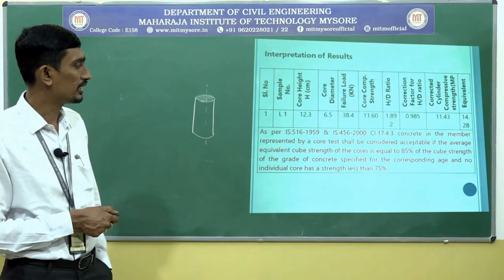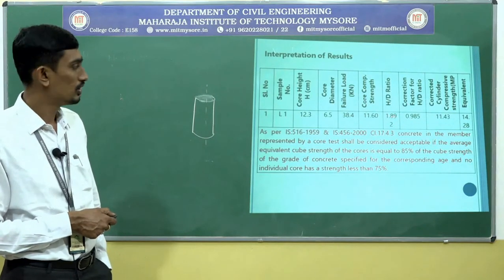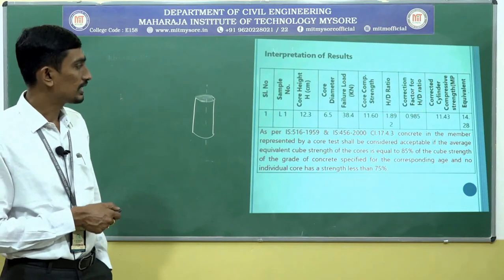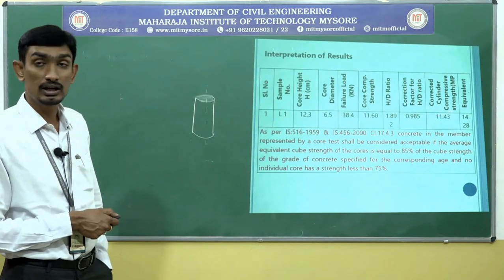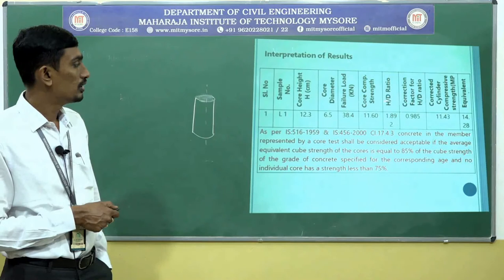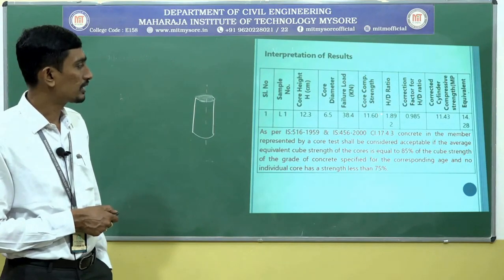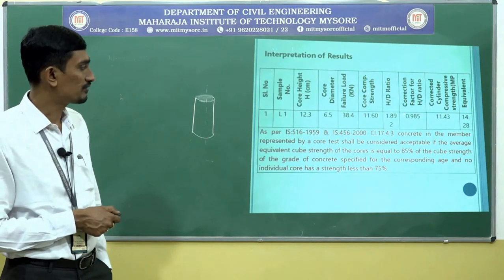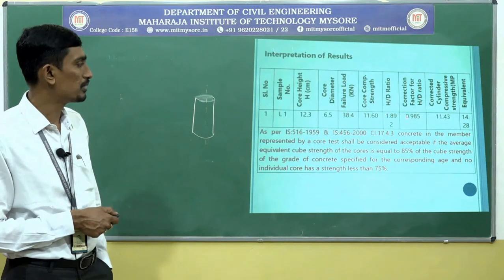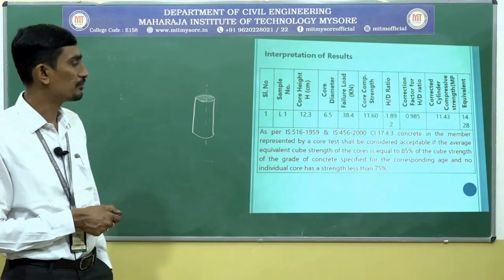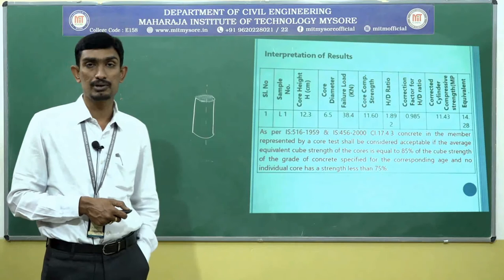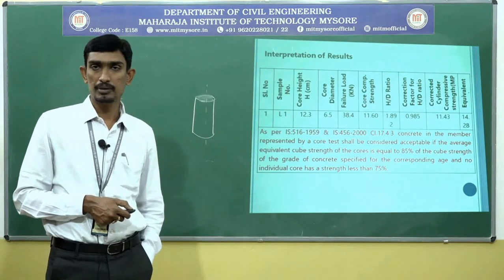That is, for 1.89, the correction factor is 0.985. So now, corrected cylinder compressive strength. How will you calculate corrected cylinder compressive strength? Multiply the core compressive strength with the correction factor, that is 11.6 multiplied by 0.985, you will get 11.43, which is the corrected cylinder compressive strength. Did you get my point?